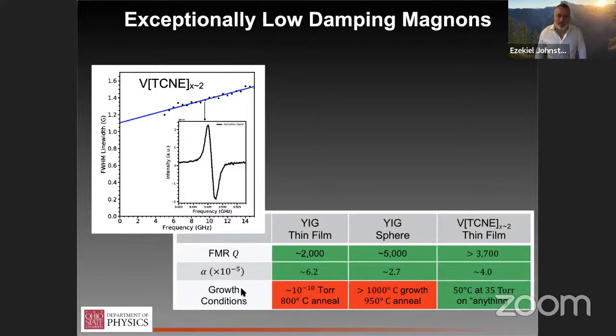The more precise figure of merit that people in the magnetic resonance community will appreciate is this alpha, and this value of 4 times 10 to the minus 5. So this Q factor is essentially the total line width, homogeneous and inhomogeneous. For many applications in quantum information, it's really only the homogeneous broadening that you care about, and this is superb. Right. So this is pretty routine. This is not one hero sample that generated this value. So this really is foundational, and we believe ultimately will be transformational for the field.